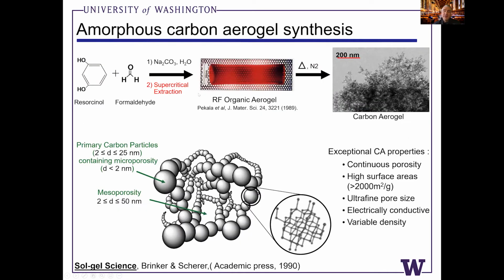So in comparison with the detonation approach, we also start with small molecule precursors. Most high explosives that are detonated are some kind of nitrogen-rich hydrocarbon molecule that's very unstable, like trinitrotoluene. We're starting with resorcinol and formaldehyde. We use either a base catalyzed or an acid catalyzed cross-linking reaction in the solvent. It could be water. More recently, we've been working with acetonitrile. And we effectively make jello.